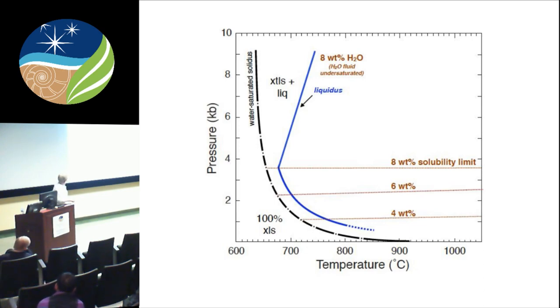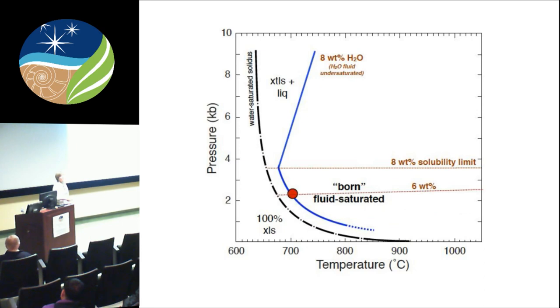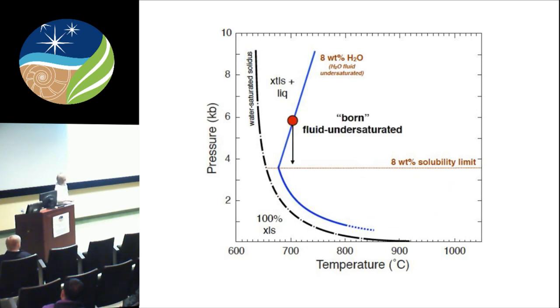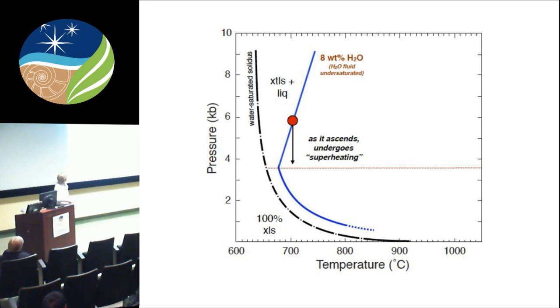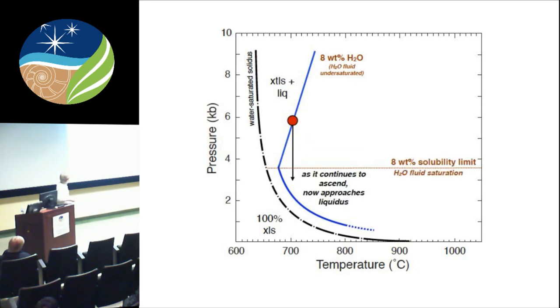So imagine what would happen if we have two melts being born at the same temperature, but one is undersaturated and one isn't. We know the fate of that one. It rises, it's going to freeze up. Those are our aplite dikes. But what about one that's born fluid undersaturated? As it ascends, it gets closer and closer to saturation, but as it ascends, it's getting further away from its liquidus. So we call that superheating. Then it crosses the solubility limit, and as it continues, it's going to eventually approach its liquidus. Okay, finally. But it's done that with quite an interval where it's been above its own liquidus temperature.